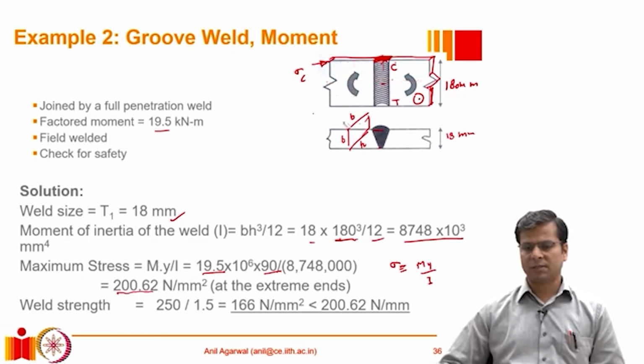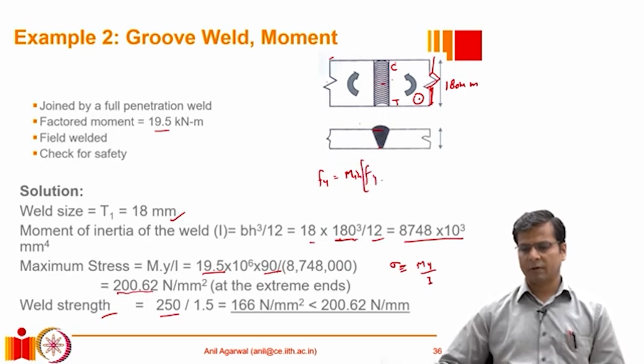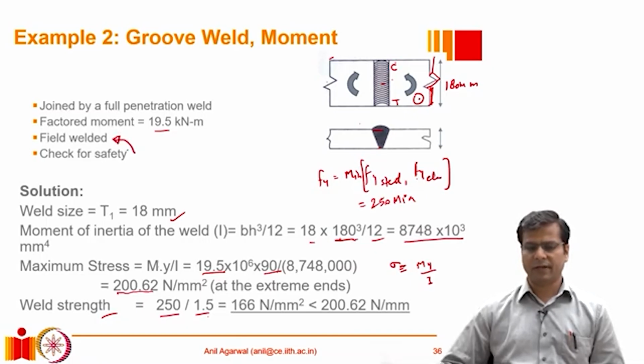How much stress is this weld allowed to take as per the limit state of design? The weld strength can be calculated as Fy, which is the minimum of the two yield stresses, Fy of steel and Fy of the electrode. So we use that, we get 250 MPa as Fy. We substitute that divided by 1.5, because this is a field weld. If it's a field weld, the factor of safety will be 1.5. We use that, and we can get the weld strength, which turns out to be 166 Newton per millimeter square, and the demand or the stress was 200 Newton per millimeter square. And as a result, we can say that this weld is unsafe because the demand is greater than the capacity.